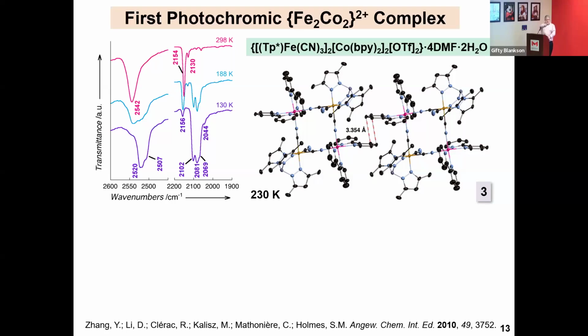So at high energy, you can see up here, this is the B-H stretch from the pyrazolyl borate on the iron. High energy for iron 3, low energy for iron 2. You go from a relatively high energy cyanide stretch, that's the bridging, that little blip there is the terminal. Remember, the terminal cyanides do this, relative to the plane of the square. And when you lower the temperature, lo and behold, the high energy absorptions go away. New lower energy ones increase with much higher intensity, reflecting that you did electron transfer.